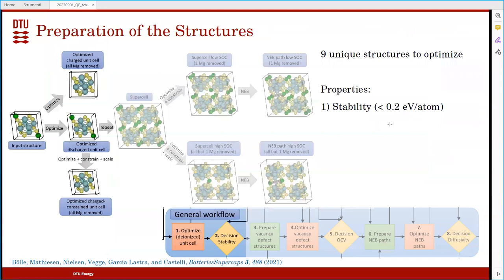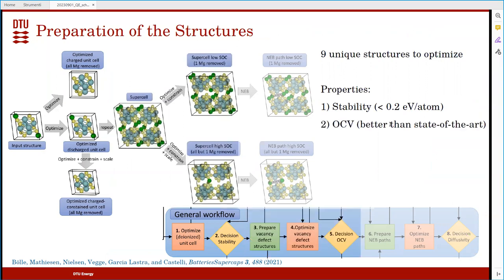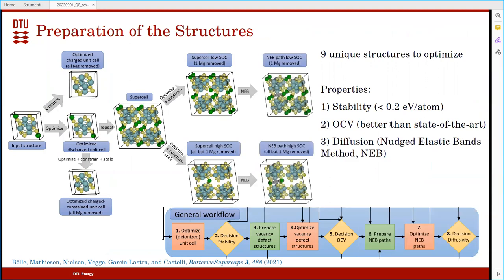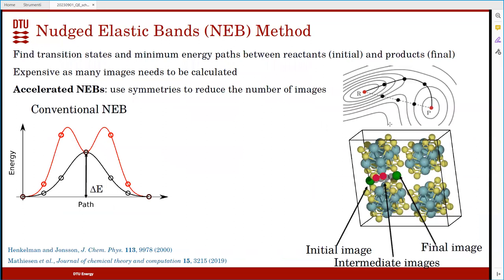I will show you. So basically what the workflow does is take these nine different structures where you calculate the stability, and then you have a threshold of 0.2. You calculate the open circuit voltage based on the energy difference between the structure with and without cations. And then you calculate the diffusion using the NEB. You take a low state of charge where you remove only one ion, and look at the vacancy mobility, and the high state of charge when you have only one intercalating ion, and look at the mobility of that.